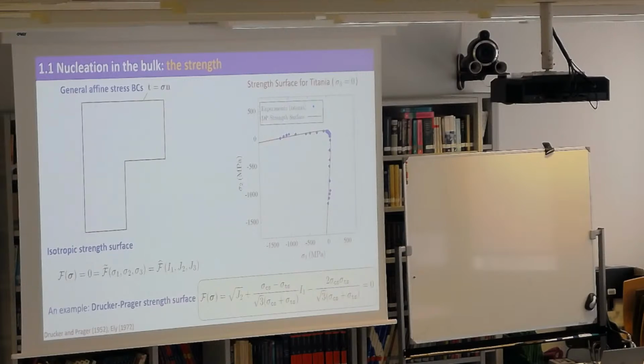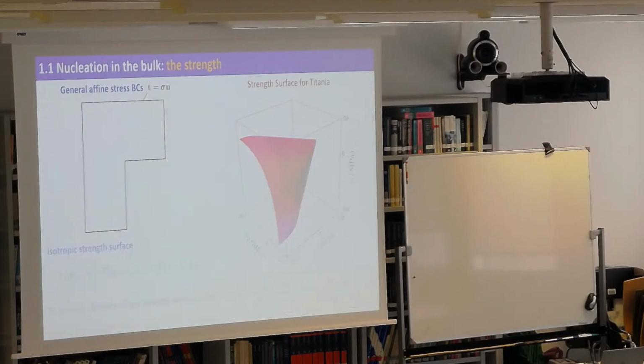And they measure things, right? So do these things break? And of course, you have a little bit, and actually more than a little bit, of randomness, stochasticity, if you like. But anyway, you come up with this cross-section of experimentally measured strength for titania, and then you go on and they say, okay, how does it look in 3D? A Drucker-Prager is a cone. Okay, fine. So the idea of strength: if I subject my material, an intrinsic property like elasticity, to uniform stress, it's going to break at some point. You measure that, you have your surface. That's it, right? One ingredient.